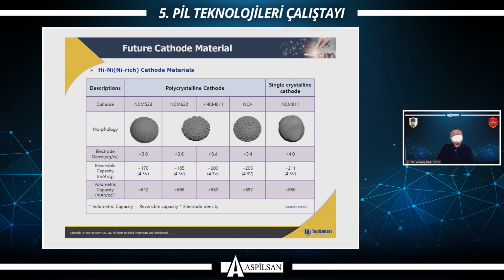These are the representative high nickel cathode materials. Polycrystalline cathode particle is composed of secondary particles with smaller primary particles combined together. But the single crystal cathode particle only consists of larger primary particles. N is nickel, C is cobalt, M is manganese. 5:3:2, 6:2:2, 8:1:1 means the molar ratio. The more nickel concentration, the larger cell capacity is realized. Electrode density is like this, and the reversible capacity is like this.